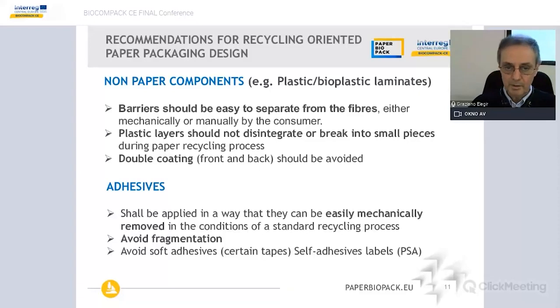Actually, with respect to design for paper packaging recycling, we can give some general recommendations, for example, regarding non-paper components, either plastic or bioplastic laminates. Ideally the barrier should be very easy to separate from the fibers, either mechanically during the paper recycling process, or manually by the consumer. When it's possible for the consumer to separate the barrier, it is normally very easy to separate it also during paper recycling. Also, the plastic layers should not disintegrate or break into small pieces during the paper recycling process, because as I highlighted in the previous slide, then it is more difficult to separate.